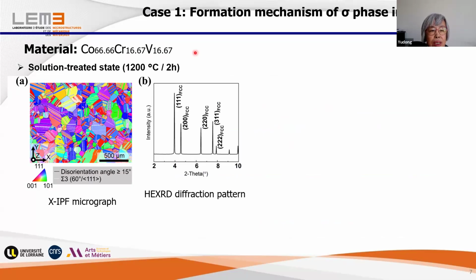After preparation of the material and solution treatment, we have a microstructure that looks like this. It was equiaxed grains, but with a lot of annealing twins inside, because this material is a low stacking fault material. I would like to say it's an ultra low stacking fault energy material. And from a synchrotron diffraction pattern we see we have only FCC phase.